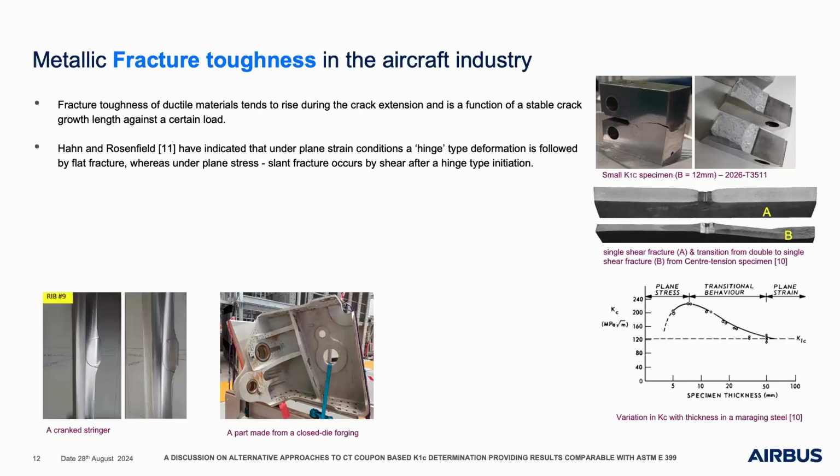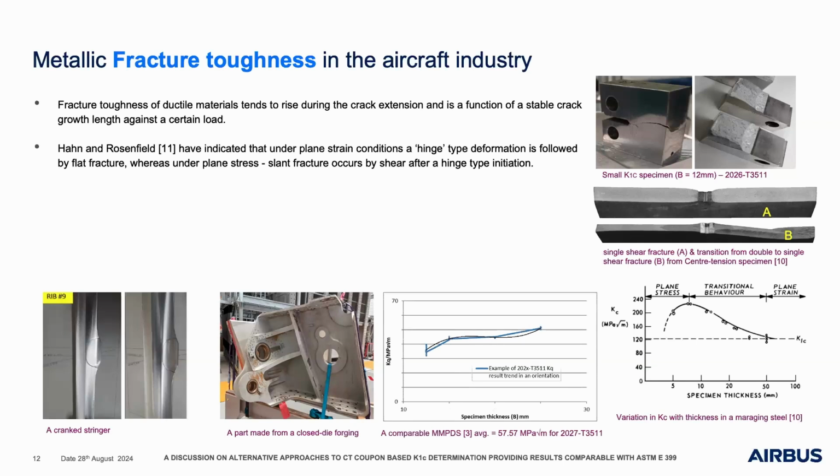Now, this is an MT specimen or a CCT specimen. This is also an image of Eols and Van Til. This is some experimental data. Say we got a certain extrusion, and from the same extrusion thickness, based on specimen size, varying specimen size, we are getting different results. And while I'm not allowed to show you the numbers there, I can tell you that the range in value of fracture toughness is quite large, quite significant.